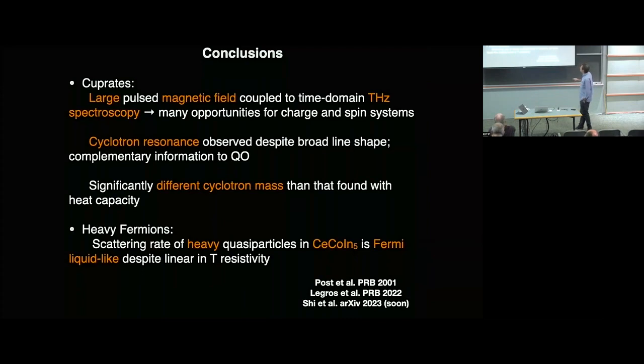The thing I wanted to emphasize was that we get significantly different cyclotron masses than those found in the heat capacity, and that's afforded by the new possibility of doing large magnetic fields coupled to time domain terahertz spectroscopy. The claim I want to make is that the scattering rate of the heavy fermion quasiparticles in CeCoIn5 is Fermi-liquid like despite the linear in T resistivity. And then I'll just stop there and take questions.